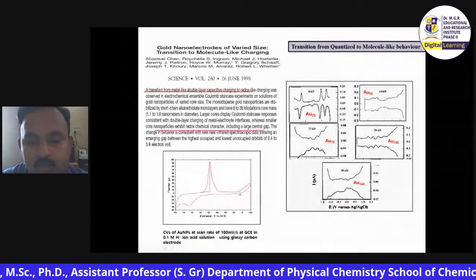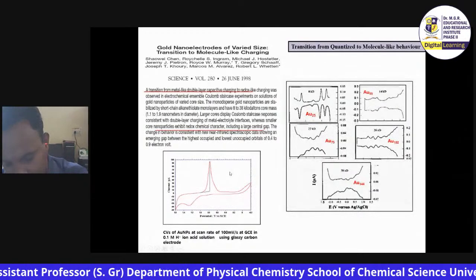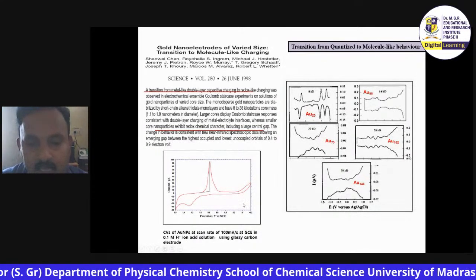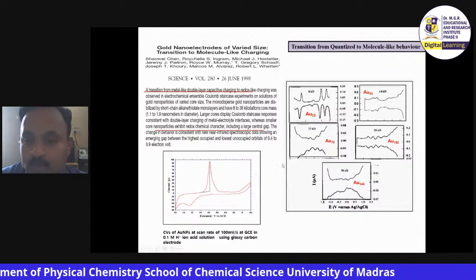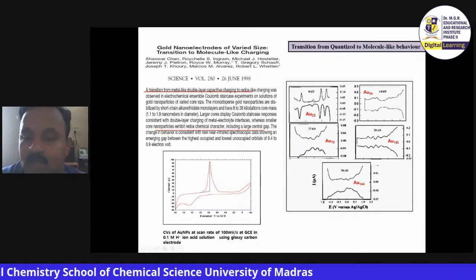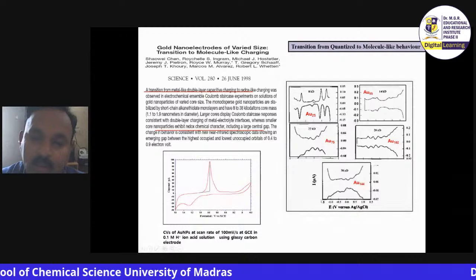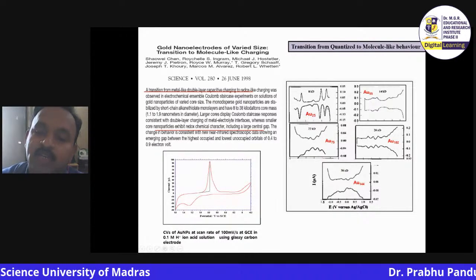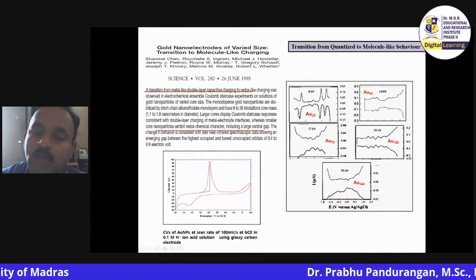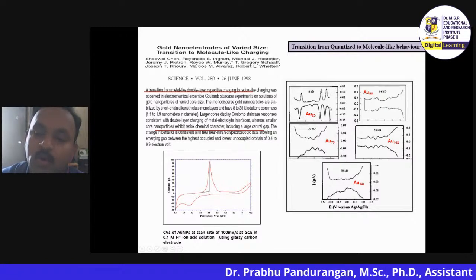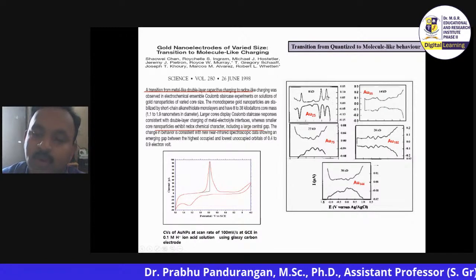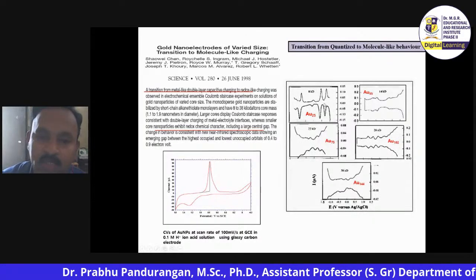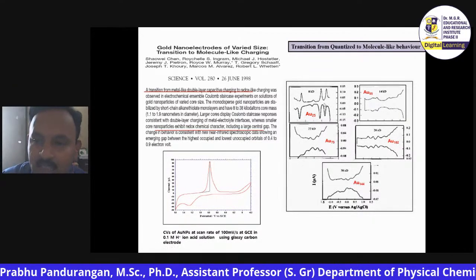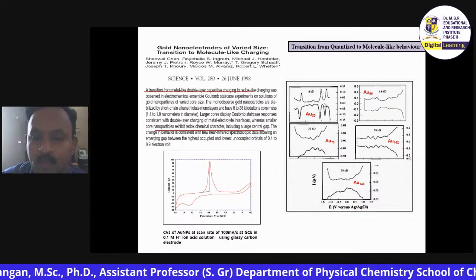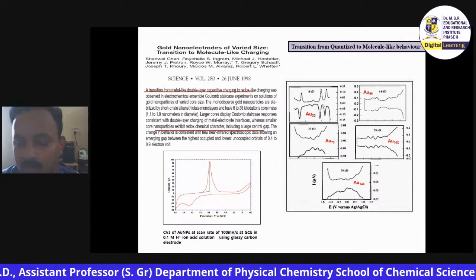The electrochemical response of gold is quasi-reversible for a particle up to 1.2 nanometer. But if your particle is exactly 1.1 nanometer, 90 to 95%, 8 to 38 kilodalton size, it will develop a HOMO-LUMO gap and it will develop a redox property like this. I'll tell you the application of this. That is the transition of a metallic particle to a molecular particle.